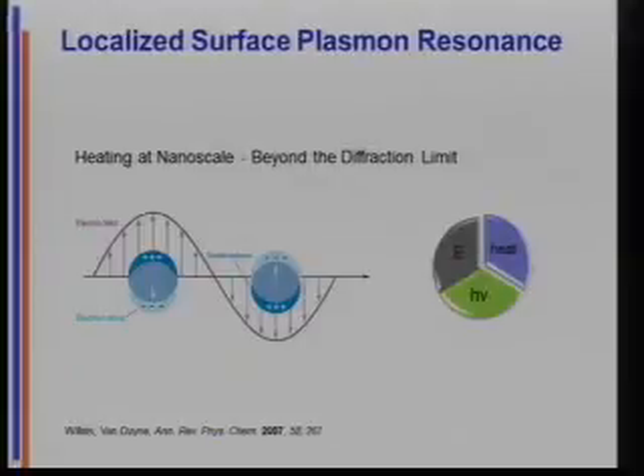Okay, so for those of you who know, I apologize for this discussion. For those of you who don't know, here's the organic chemist's explanation of this. If you have a metal nanostructure, these have an optical response. So you're irradiating these, in the case of our balls, with visible light, like 500 nanometers. What happens is you get a field or a wash of electrons back and forth in response to the electric field, because this is large with respect to the nanoparticle. So it's basically a sort of excited state. And this will eventually relax, as all excited states do. One of the things that it does is give off heat. So you end up heating nanoparticles, making hotspots on nanoparticles with visible light.